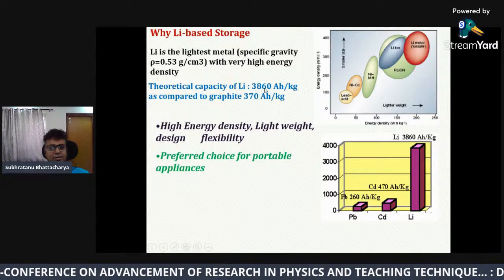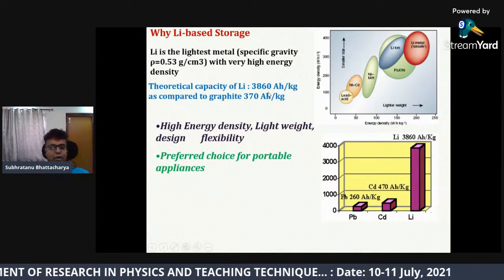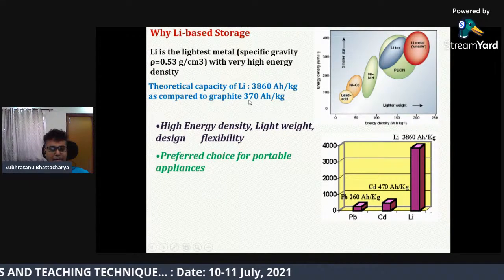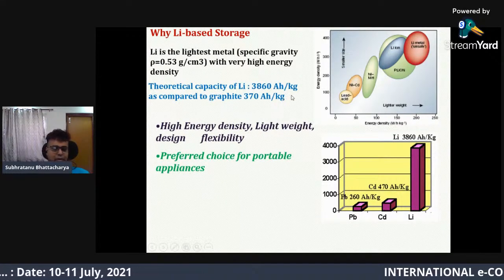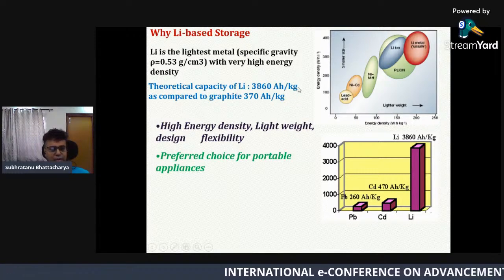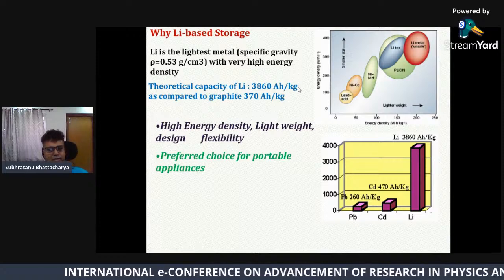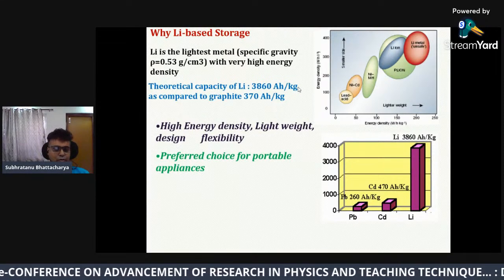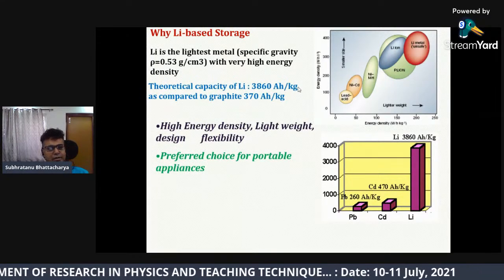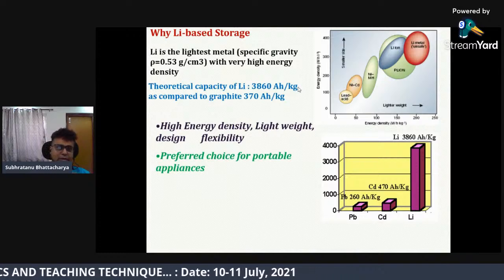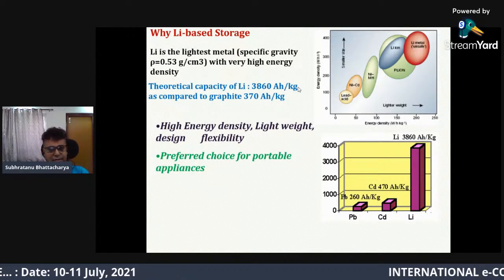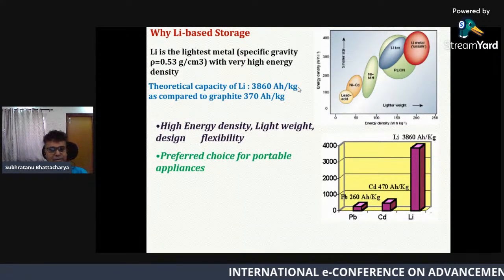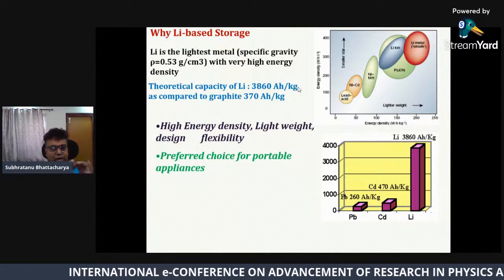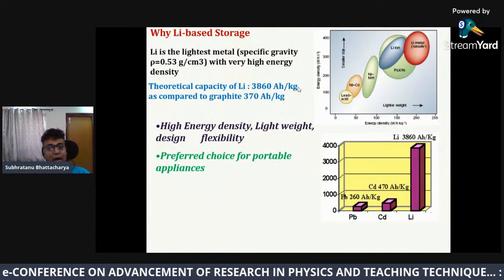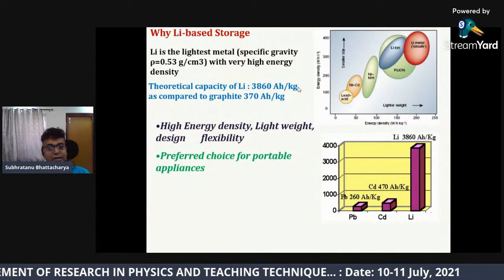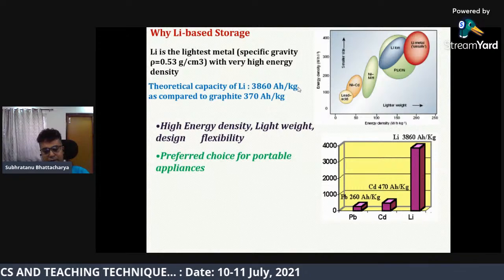Its theoretical capacity is 3860 ampere hour per kg, which is well above 10 times higher as compared to graphite. This is only 372 ampere hour per kg. So if you can use lithium, our total scenario will change. Okay, but till now we could not use lithium as anode, and the research is focused on this, how to use lithium as anode material in batteries. That is why we can call these lithium metal batteries. And nowadays the lithium batteries you are getting are called lithium ion batteries, where graphite is the anode, not lithium as the anode, as you can get it in the primary batteries.